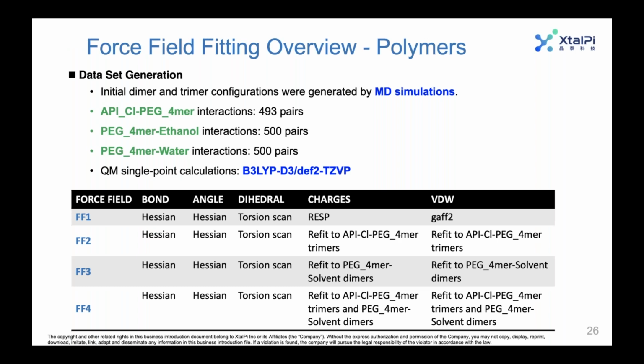We also were able to make tailor-made force fields for some of the polymers. So this is an example of that work. We came up with a parameterization procedure for that. So in that case, we looked at salt and PEG interactions, and also the interaction of the polymer with the solvent system. So to do this, we made truncated versions of the polymer. So for example, PEG 4-mer means that there were 4 repeating units of PEG. That was deemed to be large enough that we could get some of the effects of the molecule, but small enough that we could perform the quantum mechanical calculations on it.